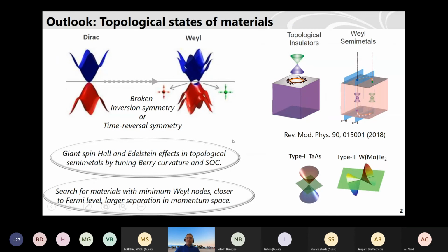Okay, then I wanted to give some outlook about such topological systems. Whatever I showed you in the experiments is not a final result set, so there is lots of development still to be done. As you know, topological states should give very large spin Hall effect or spin charge conversion. But we are not at the Dirac point or the Weyl point. Our materials are highly doped. So for example, in the tungsten telluride I showed, we are not at the Weyl point; we are above the Weyl points. So we don't know what the contribution of these topological states really is. We cannot separate it out, so that will be a good thing to think about.